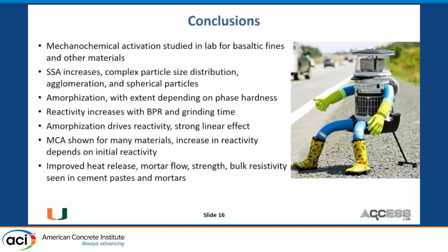But we have shown MCA for many different materials, and the increase in reactivity depends on the initial reactivity. We see in cement paste and mortars increased heat release, mortar flow, strength, and bulk resistivity improvements.